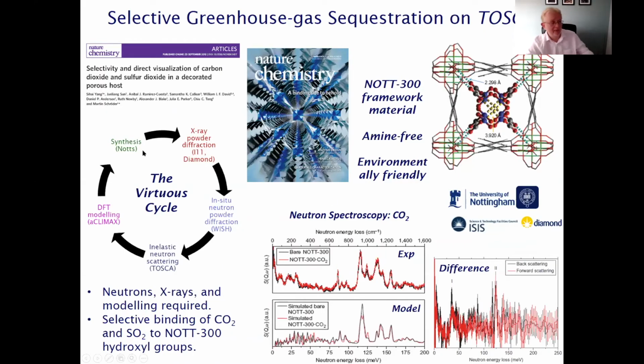And what you have to do when you have an experiment like this is have a virtuous circle. So you make your material at Nottingham and then you take it to Diamond and you do X-ray diffraction, and that gives you the structure of your framework. And then you do neutron powder diffraction, and that gives you the position of the hydrogen atoms within that framework. And then you do inelastic neutron scattering, and that gives you the nature of the gas-bound species and how they're interacting with that host. And then you put that into DFT modeling, and you use that DFT modeling to influence the synthesis of new and improved materials. And you can model very precisely how these gas molecules align. And if you have a good understanding of the structure, you can understand why they've done that aligning as well.